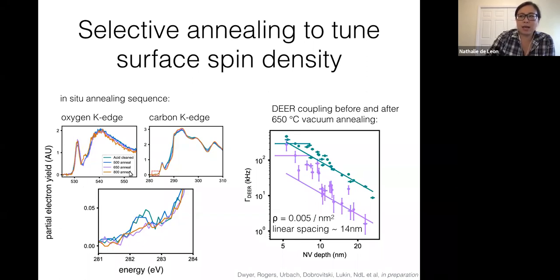So what we think is that we have a selective annealing process for this dangling bond peak. And now again, we can go back to the NV centers and look at a sample where we've characterized this DEER coupling across many NV centers, and we see this inverse scaling with depth. And then after we do the 650 degree vacuum annealing, we see that the DEER signal gets suppressed by a factor of almost an order of magnitude to these purple points here.